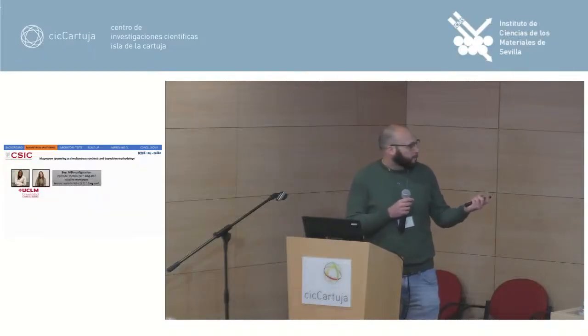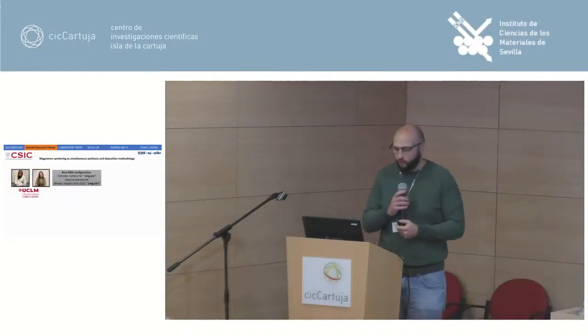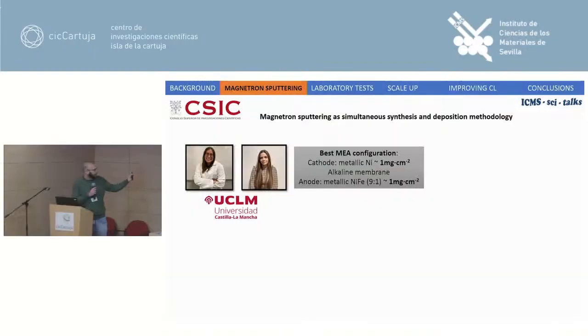So this work started with the development performed previously by our colleagues Esther and Celia during their PhD thesis work, and they concluded that the best combination of cathode and anode for an application in a water electrolysis system is the use of metallic nickel in the cathode to promote the hydrogen evolution reaction, and a metallic combination of nickel iron in the anode to promote the oxygen evolution reaction.